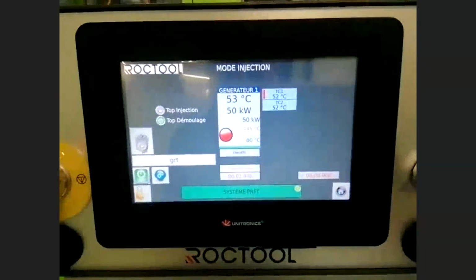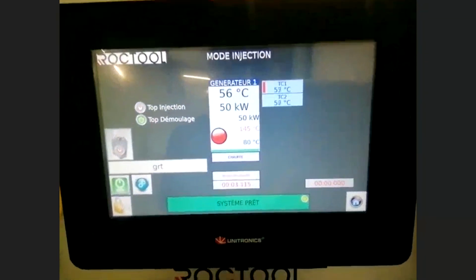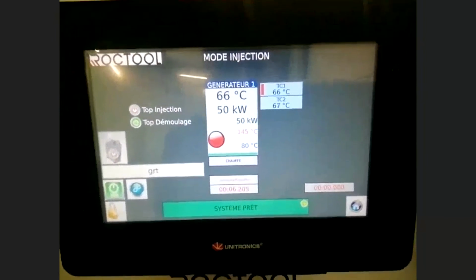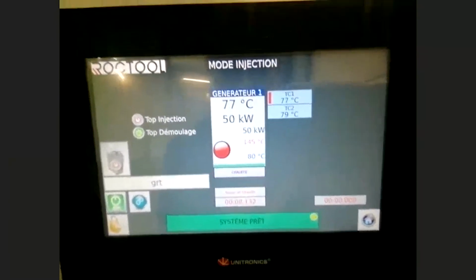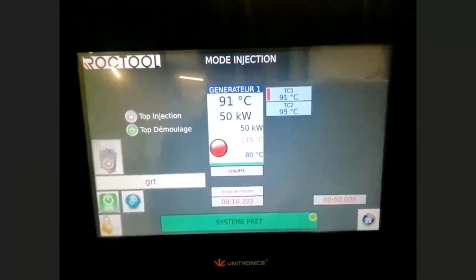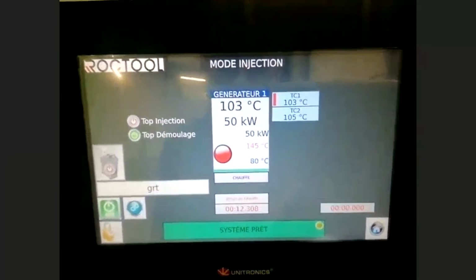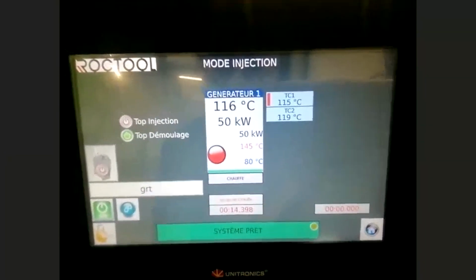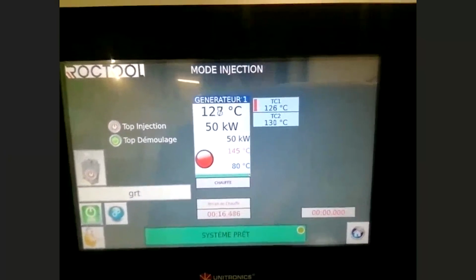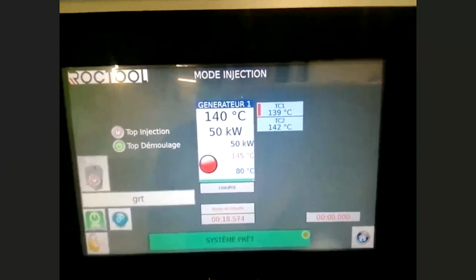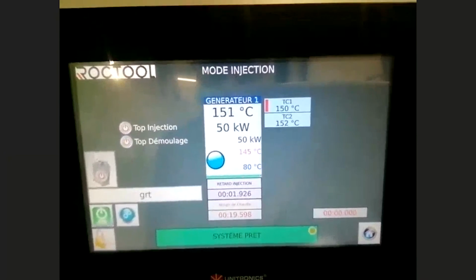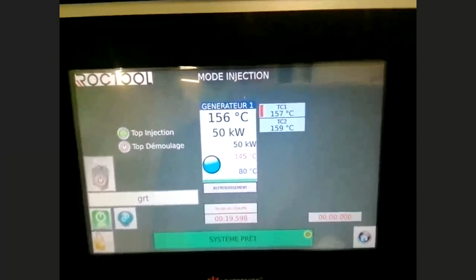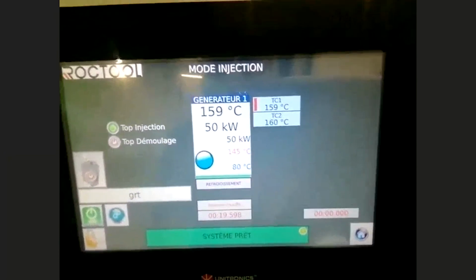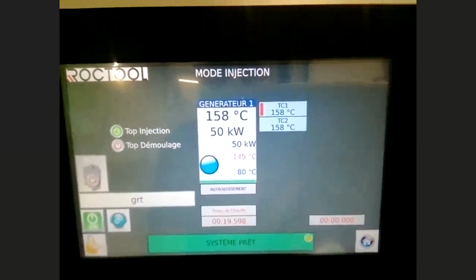If we have a look at our controller, we can see that the mold temperature is increasing and we are waiting to reach 160 degrees, as Michael showed you. The condition for that is to fix our controller at 145 degrees, and then we wait some seconds in order to have a perfect surface temperature homogeneity.